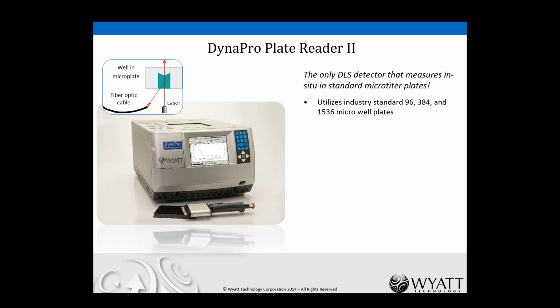All we do is shine a laser into the microwell plate and pick up the scattered signal. So it's non-invasive. There's no fluid handling involved. The DynaPro plate reader utilizes industry standard microwell plates, the same kind that are used in spectroscopic plate readers essentially, and moves the laser around between the wells, picks up the scattered light, and will give you a range of the size ranges between 0.5 and 1,000 nanometer in radius.